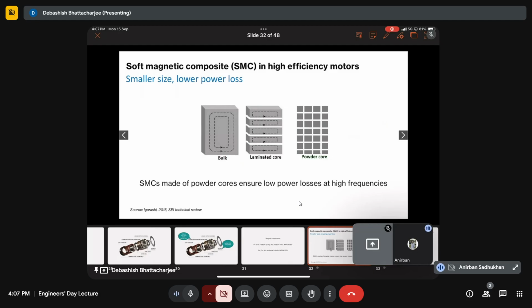Now you can ask, will magnetic flux go through this powder? It will. If you have ever dismantled a motor, you have found that these laminates of steel, which are 0.27 and above in India today, are separated by a coating. Each sheet is separated by a coating. It is separated because had it not been separated, that would have all been one conductive mass. So the net thickness would have been this. So each is separated by a non-conductive coating, either a phosphate coating or a magnesium oxide coating.